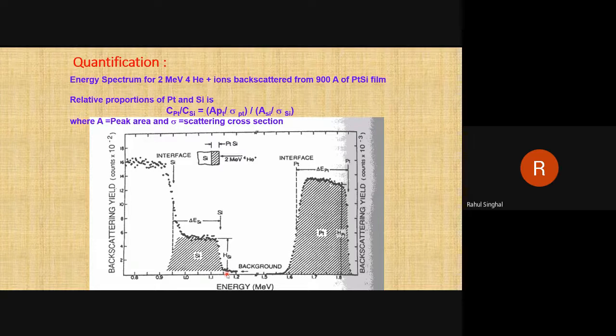Suppose you have another atom in your material with mass greater than platinum, that peak will come further ahead, after 1.8, maybe around 2.0 or 2.2, in whatever unit there is. So from this data you will get that you have platinum and silicon. But how will you be sure that this peak is of platinum only, or the smaller peak is of silicon only? So again the kinematic factor comes into the picture. I told you that by doing some calculation using the law of conservation of energy and momentum, you can find out the kinematic factor for all the atoms. It is different for different atoms, and you can easily make a table. From that you can calculate the energy of the backscattered helium ions if they collide with silicon, platinum or gold.